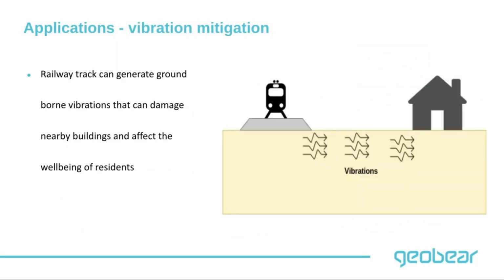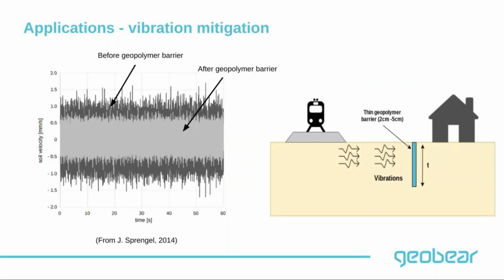One final application where we can use geopolymer technology is to create vibration barriers. So when you have a railway line near residential areas, you can actually introduce a vibration barrier using the geopolymer. So we almost install a thin geopolymer barrier that has a thickness between 2 to 5 centimeters in such a way that will stop the vibrations transmitting to nearby residents.